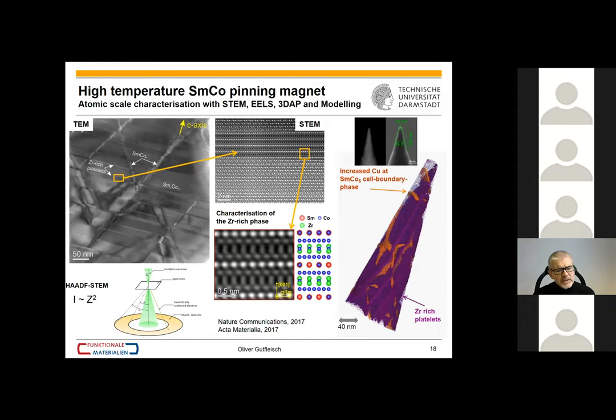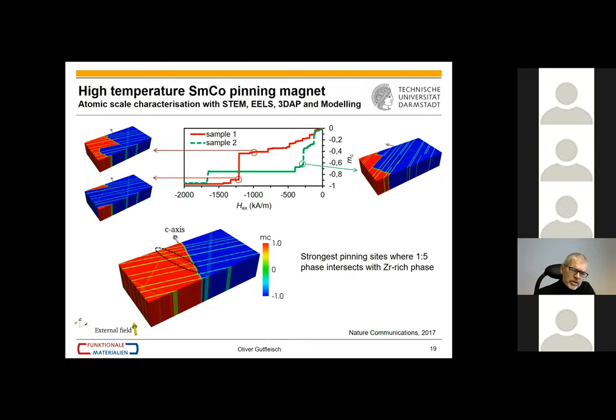But what we could show here in our relatively recent work, we looked with advanced microscopy at, for example, this zirconium-rich lamellar phase and could resolve its composition and structure with atom probe. And there's still a lot of ongoing work, for example, with our colleagues from Max Planck in Düsseldorf. You can then also see how these phases are distributed here on the nanoscale. But importantly, we could show with micromagnetic simulation that the strongest pinning site actually is the intersection of the 1-5 boundary phase with the zirconium-rich lamellar phase. So that is a new insight into a very old system, which basically supports us in our idea of trying to search for the perfect defect.